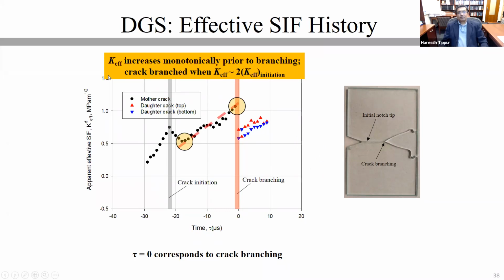As I noted before, the effective stress intensity factor increases monotonically prior to branching, and it reaches a value of approximately 2 times its value at initiation. I call this one the initiation because that's where the unloading has ended and it is beginning to increase. Once the branching takes place, you see that these values are also increasing, but they never reach a value sufficient for it to branch again. So we came to a conclusion that maybe we should increase the dimensions of the specimen so that the crack runs and produces subsequent branches, or cascading crack branch formations.